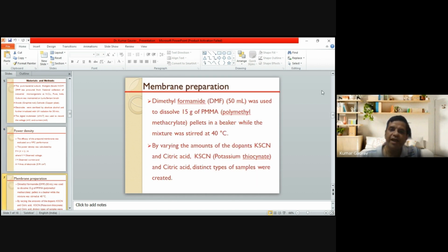After that, we synthesized the membrane. In that, we used dimethylformamide 50 ml, and we added the polymer, that is polymethyl methacrylate. The pellet was dissolved in the mixture and stirred at 40 degrees Celsius. After that, we added dopant. Dopant can increase the conductivity.